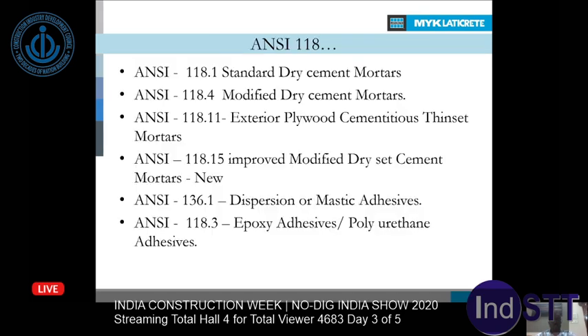Similarly, American standards are also prevalent in India. They come with different categories. A118.1 is the basic mortar, it's a C1 type, where it is not modified. And if you go to A118.4, 11, 15, they're all highly modified based on the requirements. And also they have a standard, A118.3, for epoxy adhesive or the grout that we talked about. Okay, so then again, when you buy this material, make sure these materials are meeting these standards or exceeding these standards.